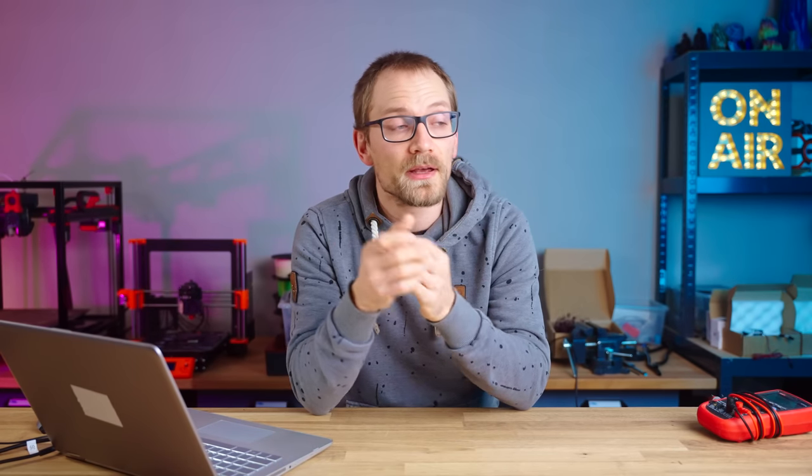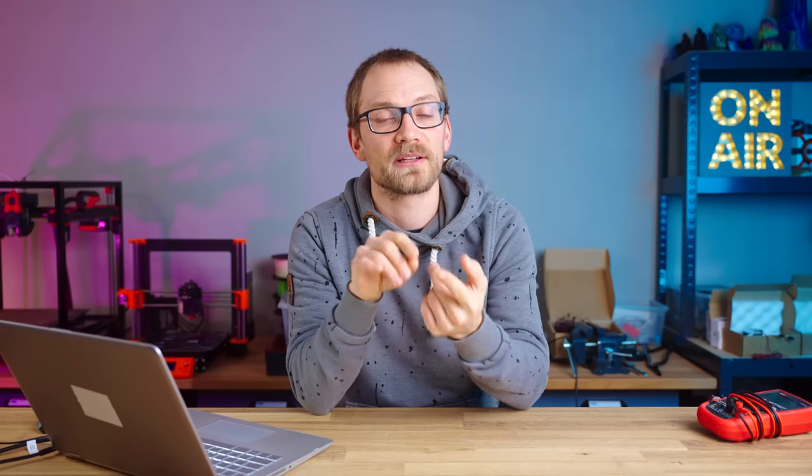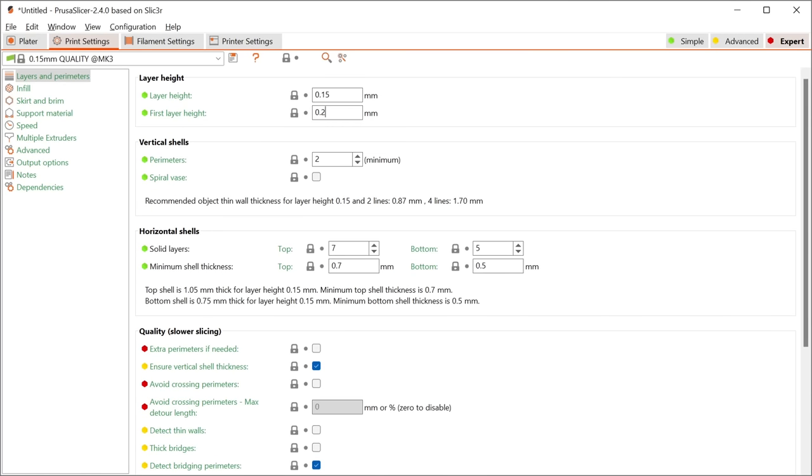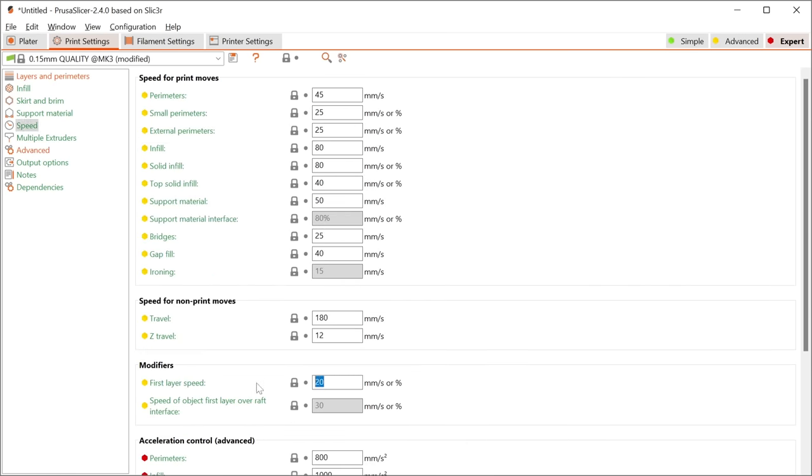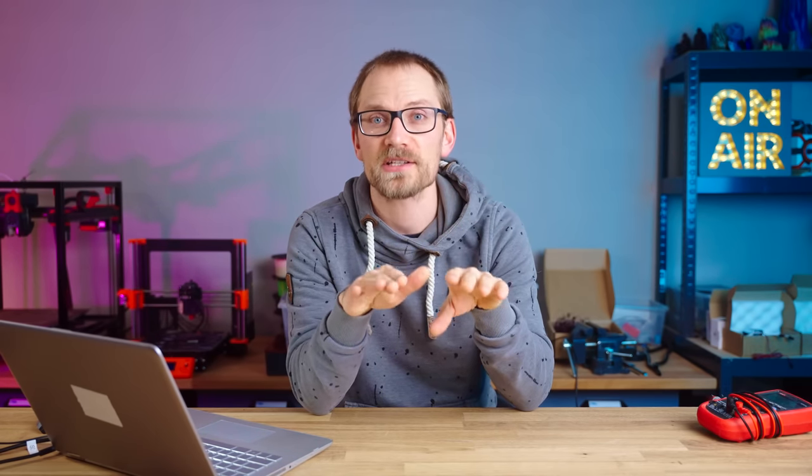You often also get a similar pattern when the bed surface is contaminated with fingerprints or grease. To fix that, I'd recommend raising the distance between the nozzle and the bed, and then using a wider and thicker first layer at a lower speed. That gives the printer a much better chance of getting adhesion even if there are imperfections in bed adjustment. The second thing I'm seeing is a problem with the model — it looks like it contains an unprintable overhang right there against the bed, and the heat from the bed keeps that freshly printed layer from cooling and hardening in time, making it more likely to curl up and cause issues further up the print.